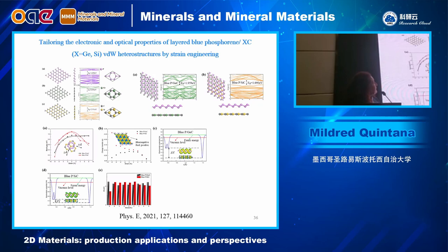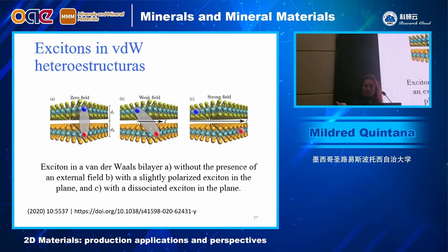phosphorene structure. And what he did is to stretch them uniaxially and biaxially, and he calculates again how the electrons behave on this structure to see how the electronic properties of these materials change. And this is very important for the future development of electronics when you want to have flexible electronics like patches or other. In this case, what is happening is that if we have one semiconducting material, we have other semiconducting materials,